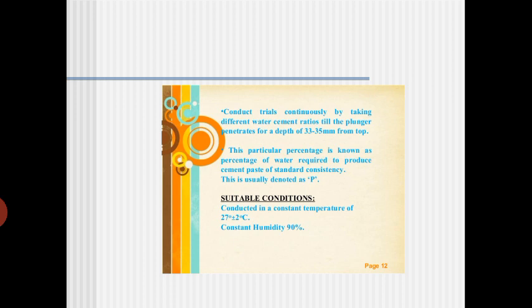Normally we conduct this experiment at 27 plus or minus 2 degrees centigrade and with a humidity of 90%. This is very important, because when you conduct this test in some cold countries, where the temperature is sometimes 0 degrees centigrade, sometimes minus 2 or minus 3 degrees, you won't get this consistency, because the water to cement ratio when you mix it normally depends on the temperature. If the temperature is cold, it will start flowing, and once it starts flowing, you won't get the standard consistency. That is why, whenever you conduct this test, make sure that the temperature and humidity are constantly maintained for at least 10 minutes till the finish of the test.